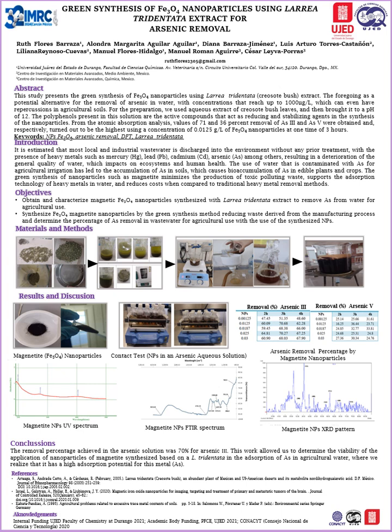The foregoing as a potential alternative for the removal of arsenic in water, with concentrations that reach up to 1,000 micrograms per liter, which can have repercussions in agricultural soils. For the preparation, we used an aqueous extract of creosote bush leaves and then brought it to a pH of 12. The polyphenols present in the solution are the active compounds that act as reducing and stabilizing agents in the